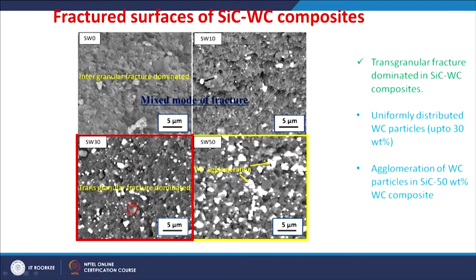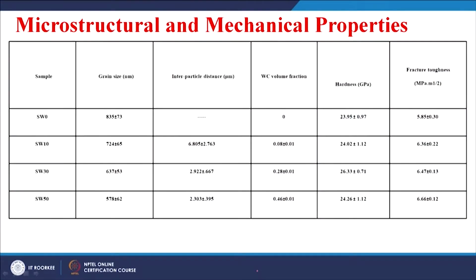Now, with respect to the tungsten carbide content, we can see uniformly distributed tungsten carbide particles in a silicon carbide matrix, whereas you can also see certain agglomeration present when you have a larger amount of tungsten carbide content. So, this SiC with 50% tungsten carbide composite shows agglomerations of tungsten carbide particles. The mechanical properties are studied for these composites. The hardness increases up to 30% tungsten carbide, whereas it slightly decreased with the 50% one,